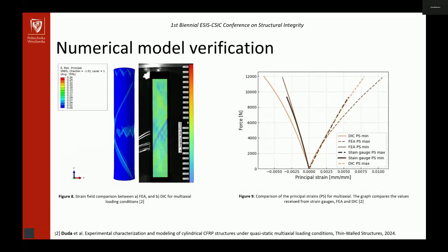Okay, so the model verification. Along with the experiments, we used strain gauges as well as a DIC system. You can see here on the left side the strain fields from the finite element method compared with the DIC. We see a local concentration along this fiber interweaving area.